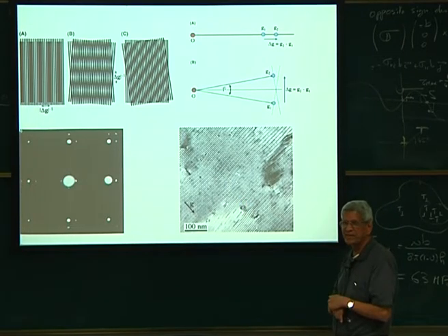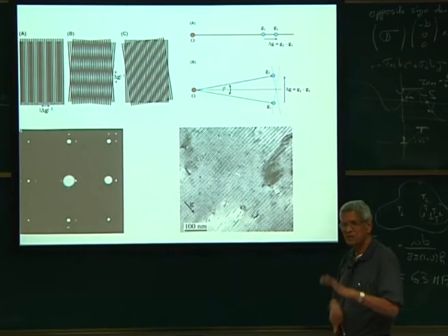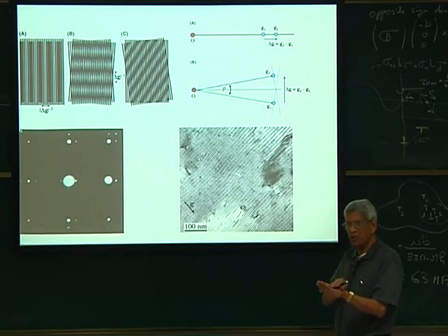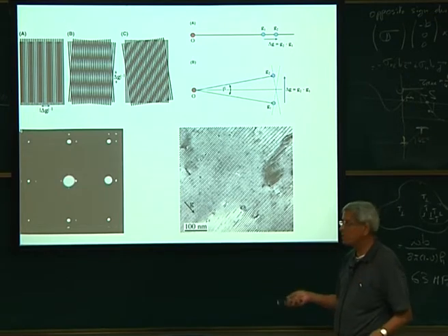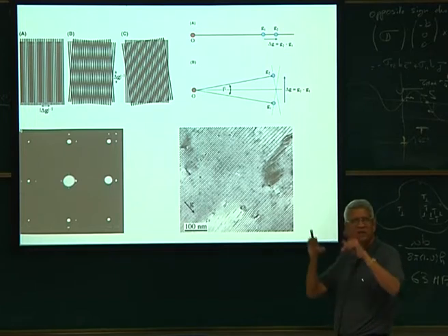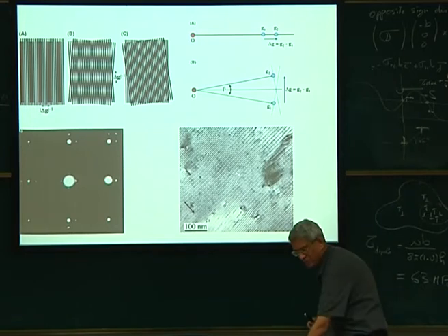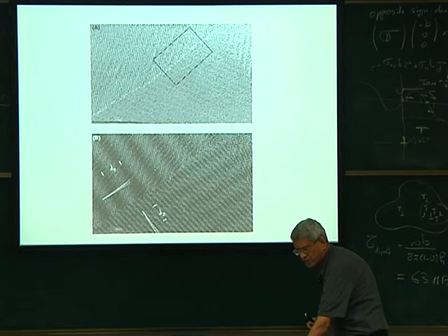With this pattern, what has been seen even before is that dislocations were actually imaged. One could see, like here, these sort of places. It looks like the way we draw the dislocation image, no? This could be obtained because if you have one lattice where a defect is there, and another lattice comes on the other side which is a perfect lattice, then there are some lattice parameter differences. The beat frequency will give rise to this sort of an image pattern, which also looks like the way we draw in a book how the dislocation looks. This I will just leave.